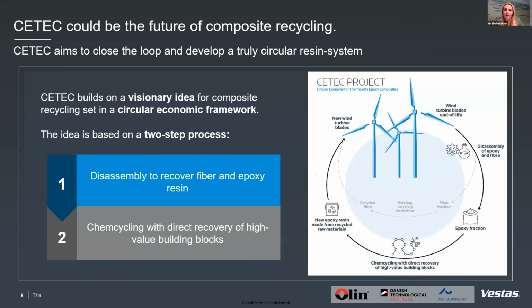But the real challenge is that it's not enough just to take these apart and do this very physical separation. We also need a chemical step where we do a chemical transformation of the epoxy, so that it's not only epoxy dissolved in some liquid, but really going back to the basic chemicals. So that means a new slight adjustment to the epoxy, but more importantly, a chem cycling step. This is what we call it, a chem cycling step, that cuts up epoxy chains into base chemicals.